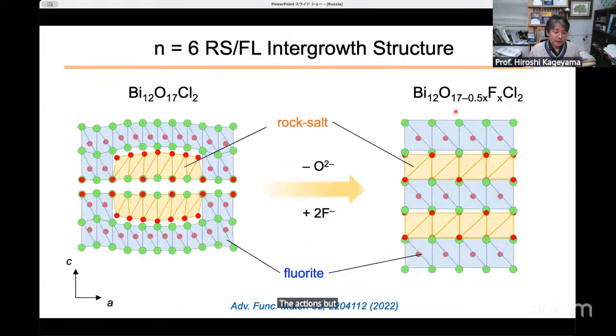But the final structure is not the fluorite structure. Once again, we got the intergrowth structure between fluorite structure and the rock-salt layers. But in this case, each layer is stacked like this. Anyway, such an intergrowth structure between rock-salt and fluorite is pretty rare. Maybe this is the first example, and the second example should be this type realized in these materials.